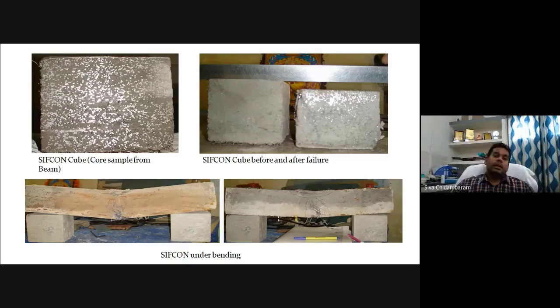If you look at the internal face, you can see this first image. This is the cube specimen we have dismantled. We have taken the core from the prism. This is how the internal structure will be. Even with the perfect orientation, perfectly made, you can see exactly in this portion that fiber presence is very low. I have tried my maximum effort to make it a wonderful quality, but still there are human errors. It's very difficult to control at the lab level, and even more difficult at the site level.